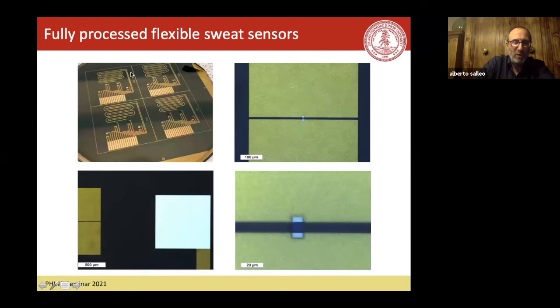So here you see, actually this is designed by Yasser Khan in the Bao group. This is to collect sweat and see how fast you sweat. And here's our little devices. So here they are, big electrodes with small device. This is just a design that we went with, but of course you can change the design at will. Also notice that these electrodes have to be completely insulated because there's electrolyte on top of it. If the electrolyte touches the electrode, all your current will come from that process, and you also have some electrochemistry going on. So this is all covered except this tiny little opening where you have a little bit of polymer,